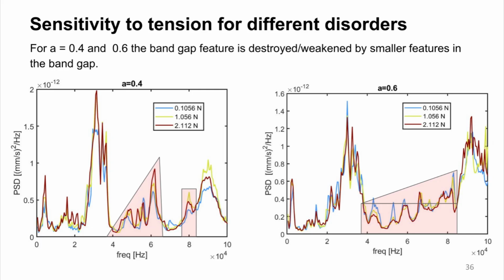For higher perturbations of 0.4 and 0.6, I find that the band gap region is not as strong and wide, and it is weakened by some of the features that appear in what was originally a band gap region. Like for 0.4, I see that around 5 kilohertz there are some of these peaks, and there's another peak around 8 kilohertz, whereas for perturbation strength of 0.6, I find that between 4 kilohertz and 8 kilohertz there are multiple peaks appearing which weaken the band gap region. However, the robustness under change of tension is still maintained for these curves.